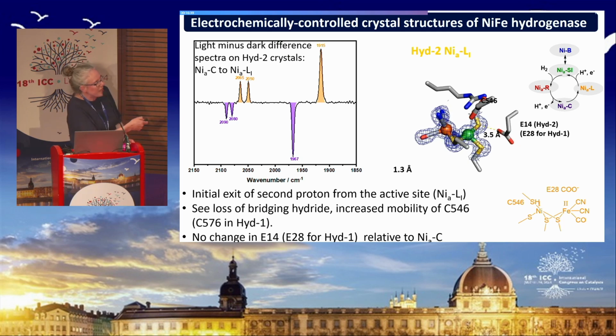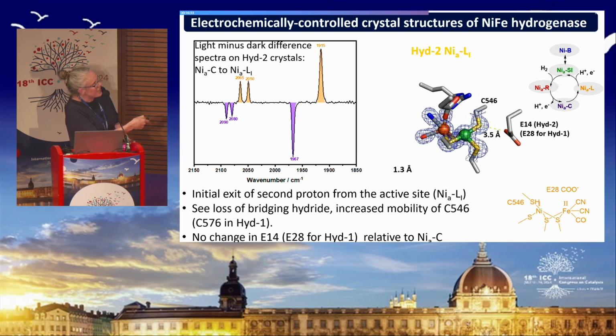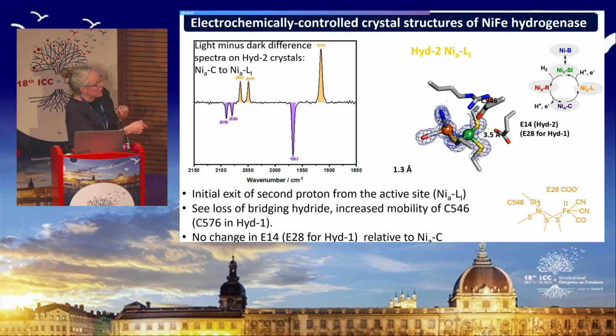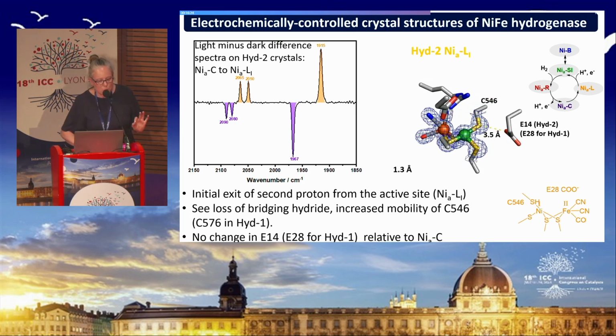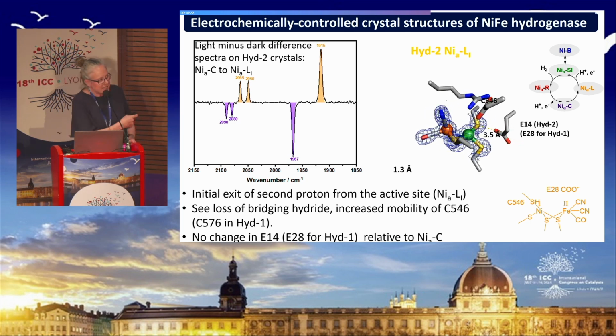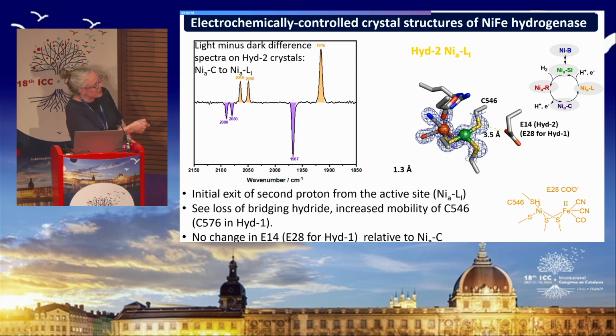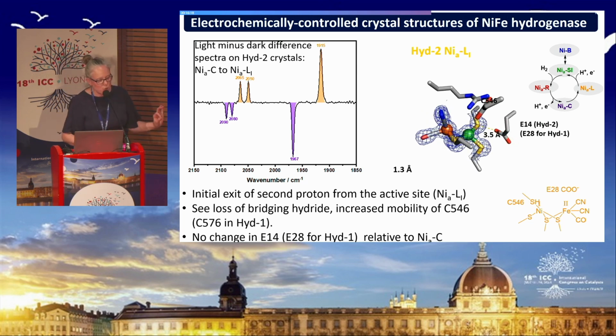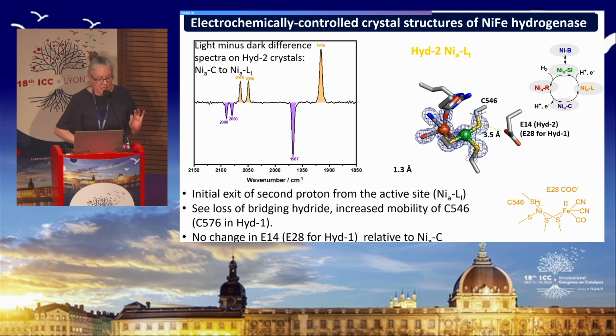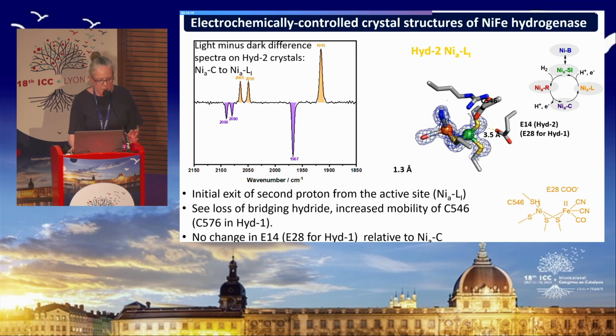Interestingly, I've also included this glutamate carboxylate side chain here so that I could point out to you that we see no change of the position of that side chain in this nickel L1 structure relative to what we saw in the nickel C structure, and that's going to become important in a moment. The position of that glutamate side chain is consistent in every single one of the intermediate states of hydrogenase that we've seen so far.